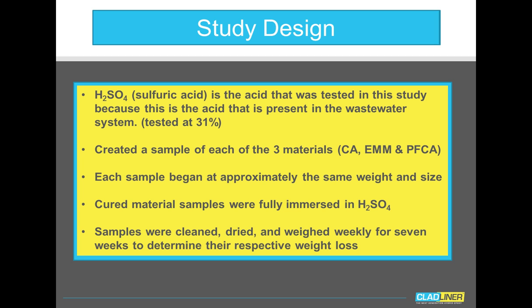So let's look at our study design. As I mentioned early on, sulfuric acid is a byproduct of H2S, or hydrogen sulfide. So this is the acid found in the wastewater environment, and as a result, this is the acid selected to test the chemical resistance of these components in this study. 31% sulfuric acid was chosen in order to get accelerated results, without having to wait multiple years. A sample of each of the products was created, a cured core sample, of calcium aluminate, epoxy modified mortar, and pure fused calcium aluminate.